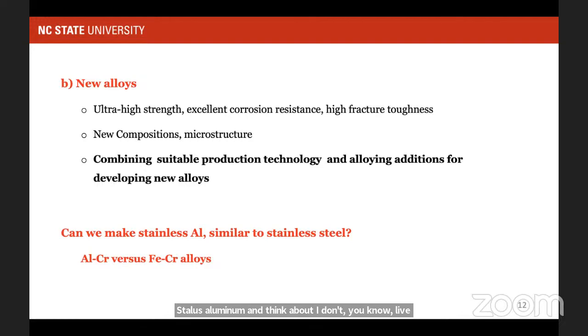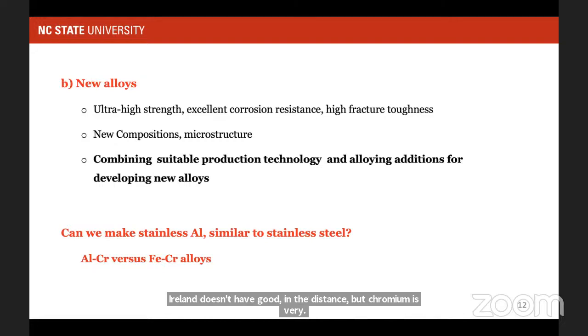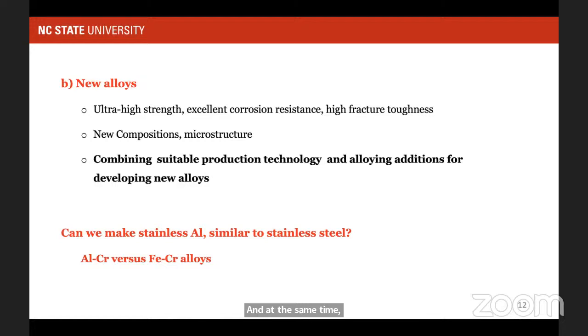So in iron chromium alloys, iron doesn't have good corrosion resistance, but chromium is very corrosion resistant. At the same time, chromium is a very active metal, right? As you put it in air, it forms a chromium oxide layer immediately. Now, if I make iron chromium alloys, iron dissolves, chromium stays as chromium oxide on the surface, and eventually forms the chromium oxide layer and gives all the corrosion resistance. So it should be a simple phenomenon. We can do that for aluminum, right? We can make aluminum chromium alloys, or similar to iron chromium alloys, we can make a whole aluminum series.